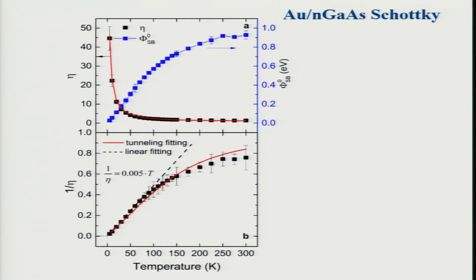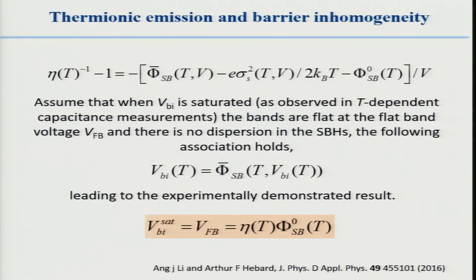So here I'm coming to actual data and going to low temperatures. You see we're going down to 5 Kelvin. The zero voltage Schottky barrier height starts off, and this is the region most people were in until they could go down to low temperature. But notice that it goes linear, and it intercepts 0. Okay, the zero voltage Schottky barrier height is going to 0. And the ideality is going up; ideal junctions have ideality close to 1, and it's going up. But when you plot the inverse of this, it's also linear and extrapolates to 0. So we're getting these two results because we can go to low temperatures. And this we see on all of our junctions, this linear dependence, and essentially that agreement with the linear dependence is canceling out in this relationship.